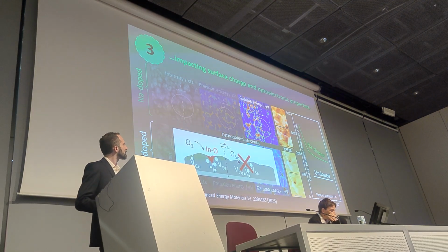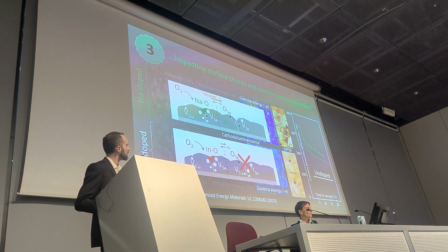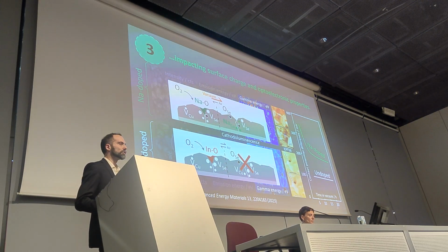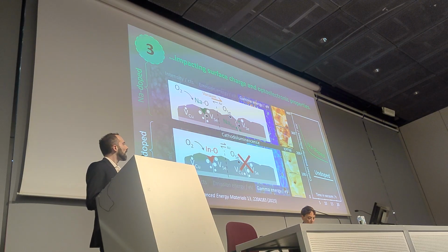So all these results support our hypothesis that exposure of CIGS films to air is detrimental if we don't have any sodium, because you end up forming indium oxide, and it's an irreversible process. But if we have the oxygen and the sodium in it, then we can first of all passivate this selenium vacancy by forming oxygen selenium, and if we are putting an excess of oxygen, well then sodium is acting as a sacrificial getter, and it forms sodium oxide phases. There are byproduct phases that we know, and some of these can be reverted back if we put the films into vacuum.